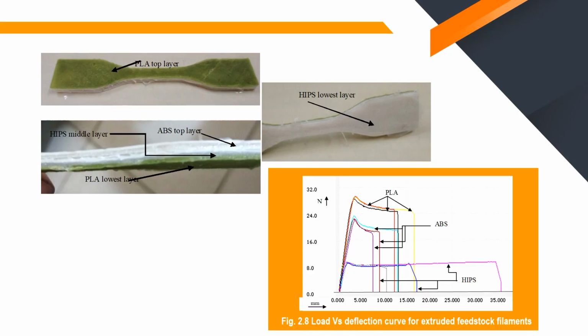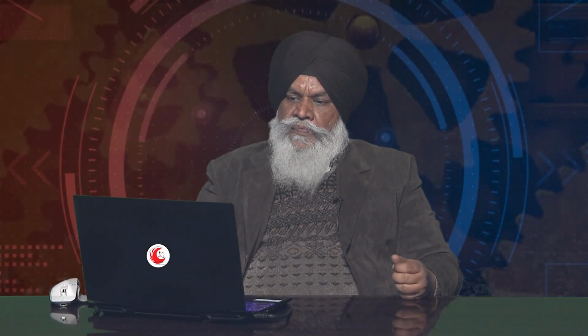You can see over here, this is the standard ASTM D638 tensile coupon. Here you can see the top layer is of PLA, here the top layer is of ABS, here the top layer is of HIPS. Load deflection diagram, we can call it a stress strain curve also. When I use a single material, this type of multi-material or functionally graded structure has not been printed, but a single material like PLA, ABS and HIPS has been printed. Now what happens when we use this type of hybrid material?